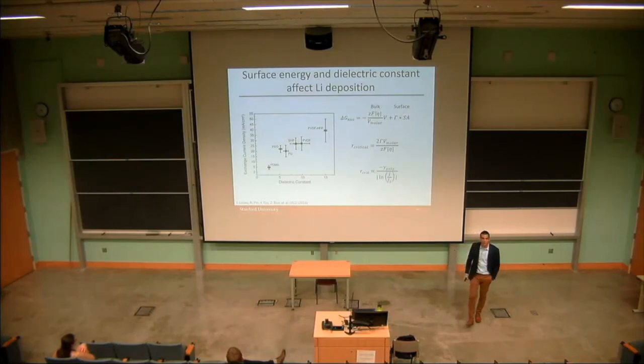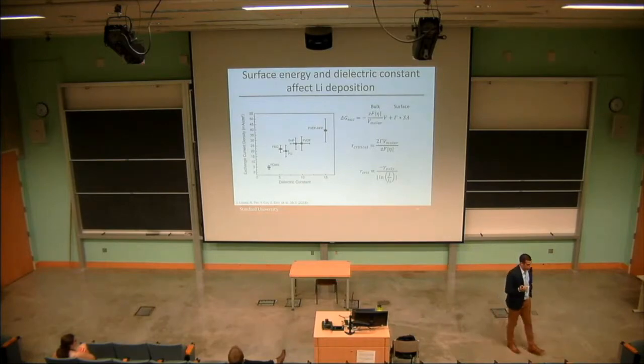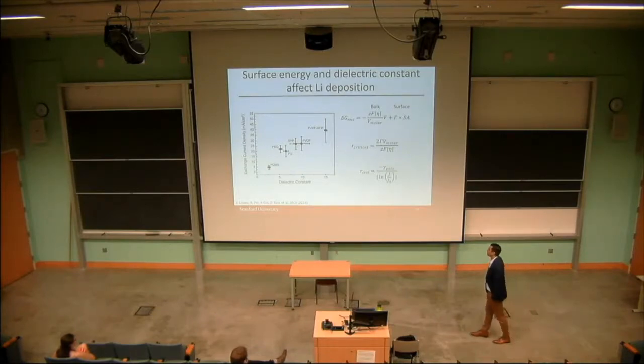So looking at exchange current density, as I mentioned, that's hard to measure, but fortunately it has a proxy as the dielectric constant of the polymer material. And we understand this as the dielectric constant is really how well the polymer can solvate these ions. And so the exchange between the surface and the polymer coating happens better or more quickly in a high dielectric medium than it does in a low dielectric medium. And this is a relatively straightforward parameter to measure for a polymer, and so we're using this as a descriptor here instead of the exchange current.